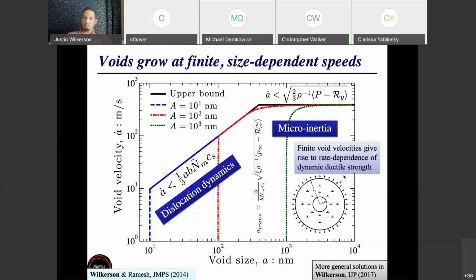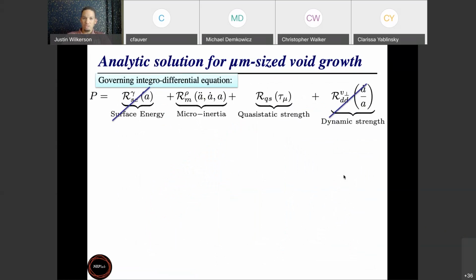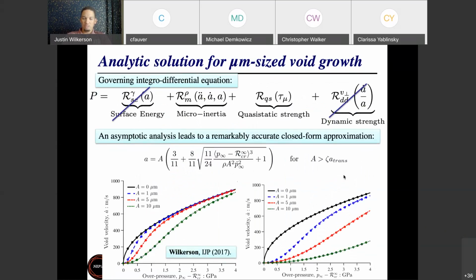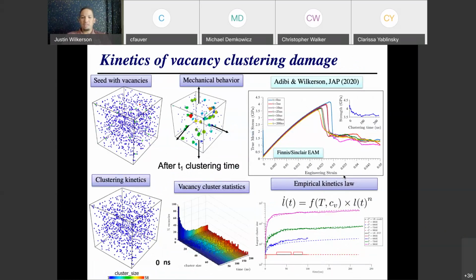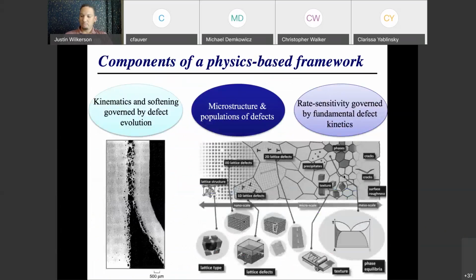And so that's going to put some upper limit on how fast damage can evolve, which is going to put an upper limit on how fast damage can relax the stresses. If you can't relax the stresses, then the stresses just continue to climb, and that's how you get to these really high spall strengths that we were observing experimentally earlier. Okay, I will skip this. We also have kinetics laws for vacancies clustering into little nanovoids, but I will skip that in the interest of time.